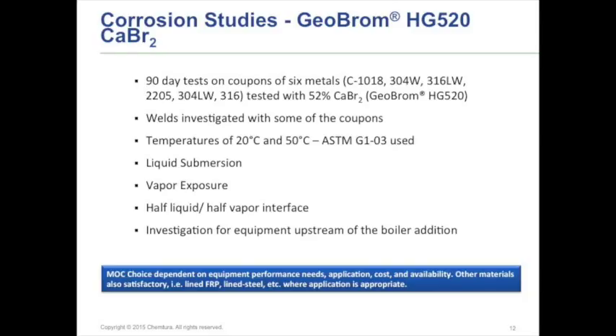The corrosion mechanisms you're looking at here are either direct condensation of hydrobromic acid on the surface, or you potentially have hydrobromic acid contributing where you've already got sulfuric or hydrofluoric acid condensing. And then you have salt formation, where you could have a situation with changing loading, with a higher temperature and a lower temperature, and then some salt precipitates out on the surface. Then you could also have the gas corrosion of HBr. Typically, you really need much higher temperatures than where we were seeing corrosion here. The corrosion studies we did, that's kind of the summary on the EPRI piece of it.